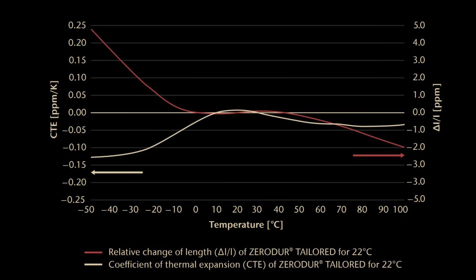This graph shows the relative change in length and the corresponding CTE for a high grade of Zerodur that is optimized for the use at room temperature. And if you look at the CTE here, it's somewhere around 0.01 ppm per degree. So it's about 10 times lower than the value specified for standard Clearceram.